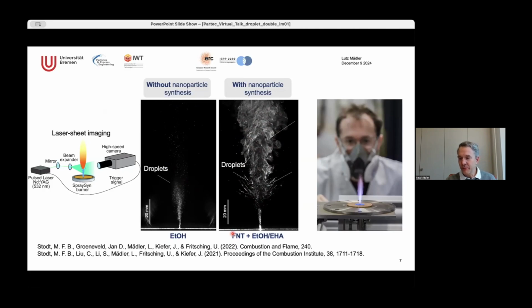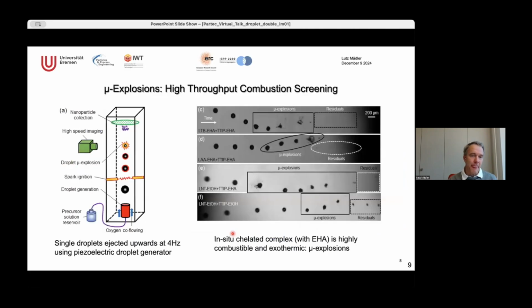So the metal inside makes a huge difference, and that's why my group has set out on this journey of really looking at the individual droplets and what they are doing, and how this whole reaction and getting into the gas phase happens. And we do that with what we call single droplet combustion experiments. We call these experiments generic experiments. And so we basically have those nanoparticles here, and those droplets here, and then we let them fly. We ignite them.